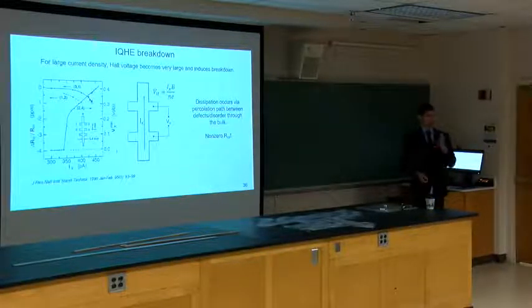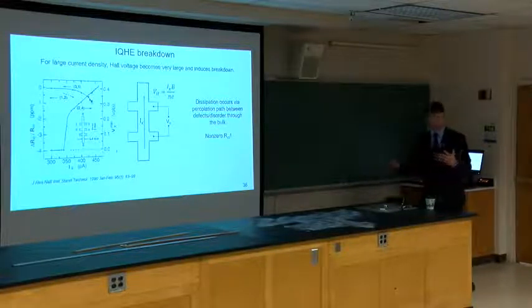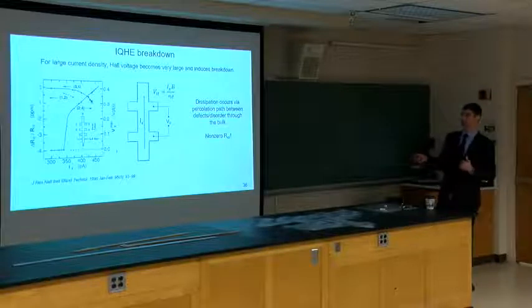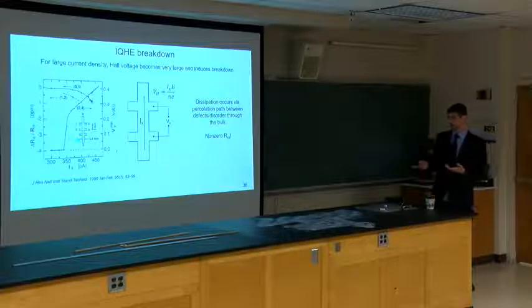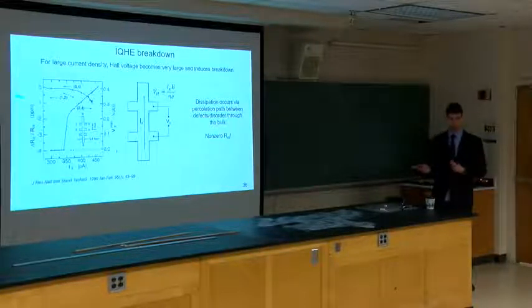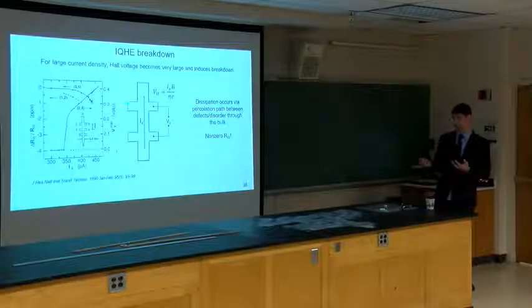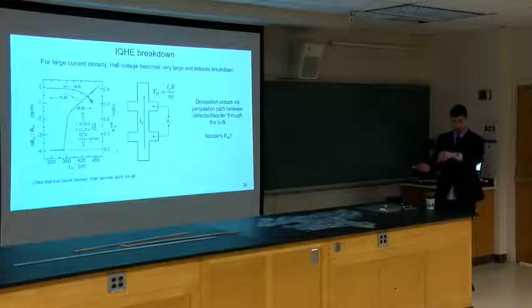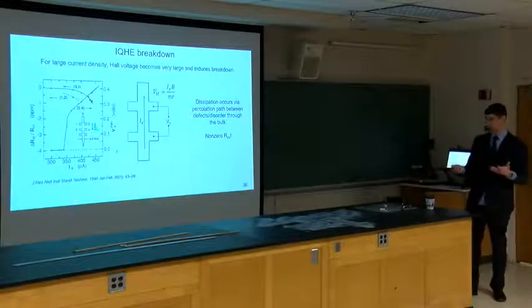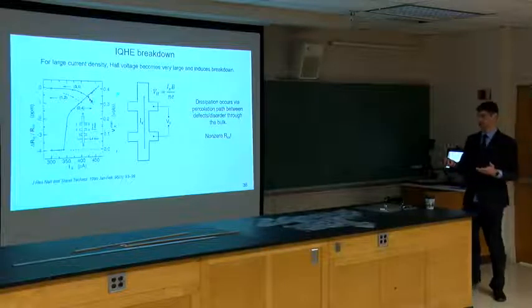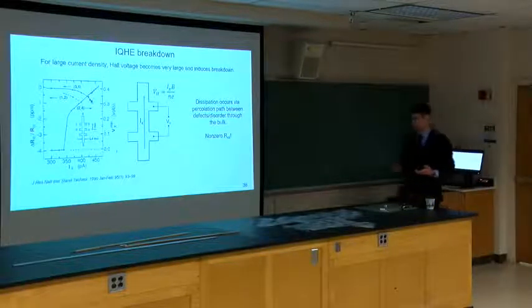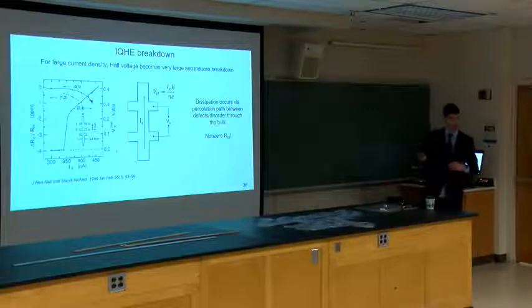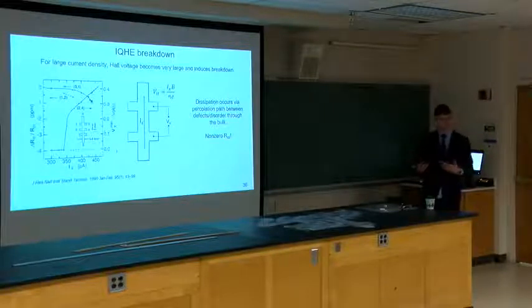So those are trivial, and once we can remove those factors, because they can be a problem, is there actually a real breakdown of the quantum Hall effect? Well, yes, of course. If you apply very, very large current densities, and specifically if you're near a plateau transition, you can get a percolating path that will exist across the sample. And as a result, you'll get a rise in Rxx or a voltage that shows up here. And that is real dissipation. So it's basically an actual breakdown of the state.